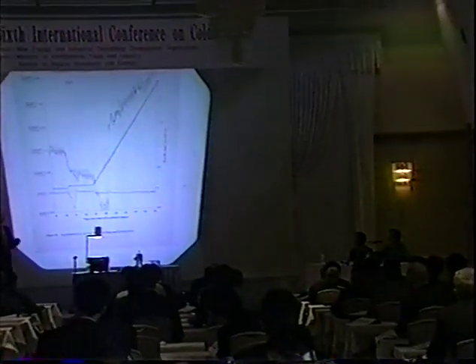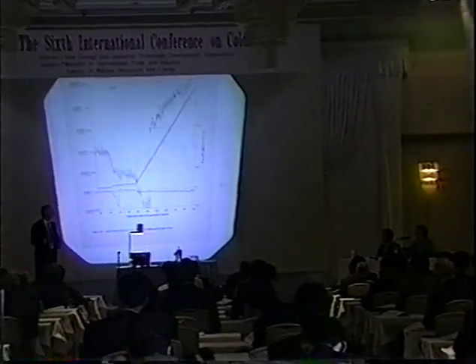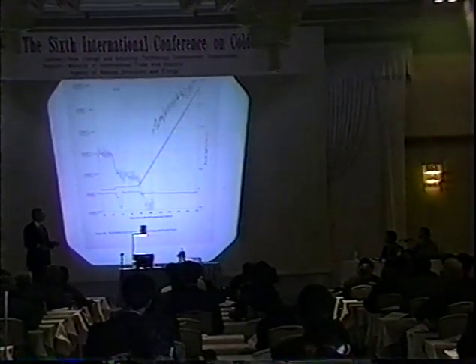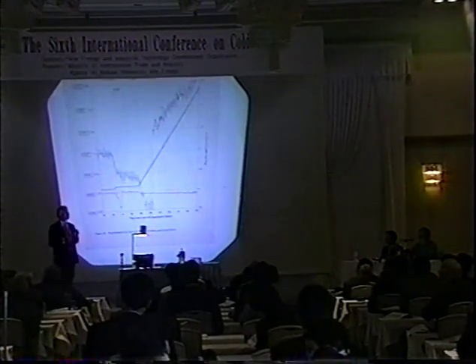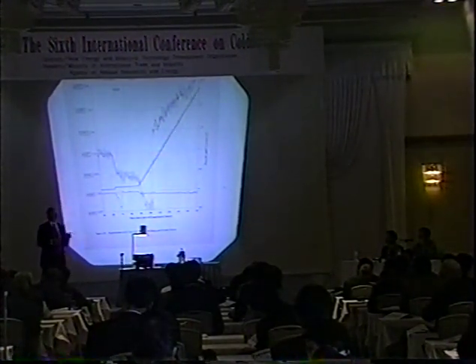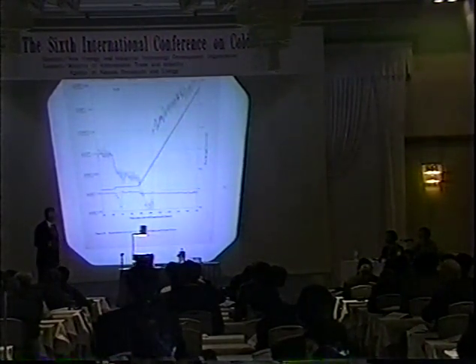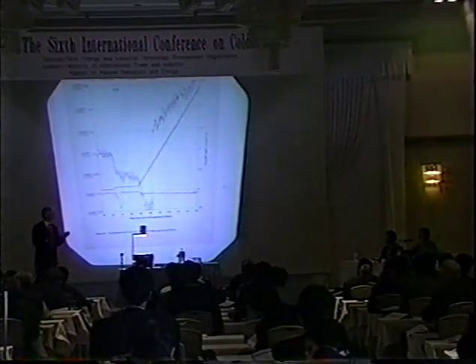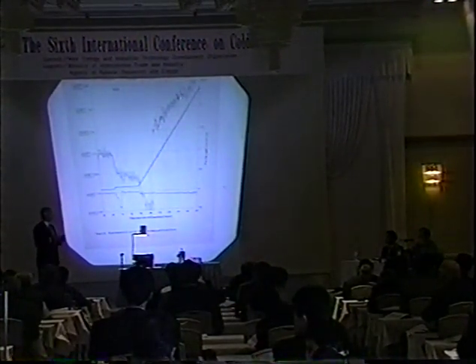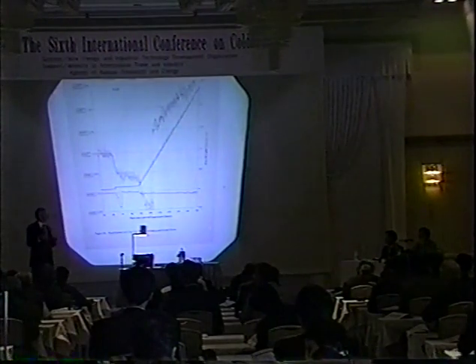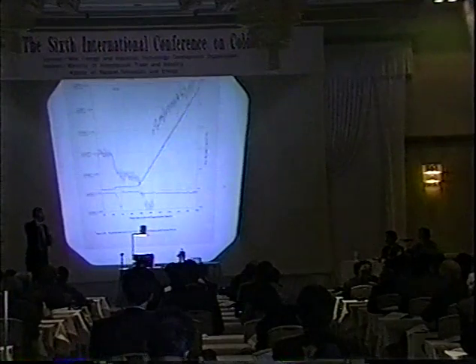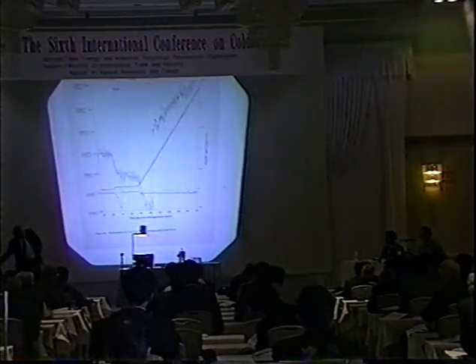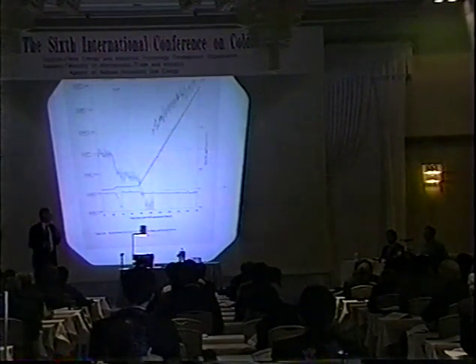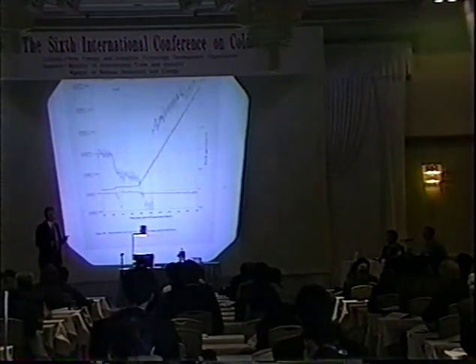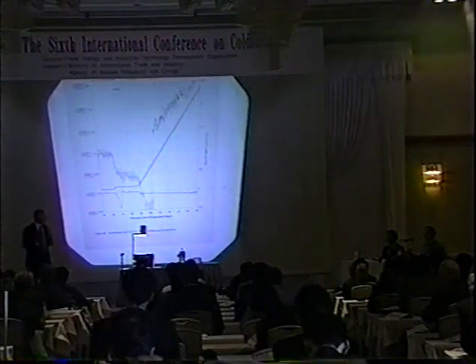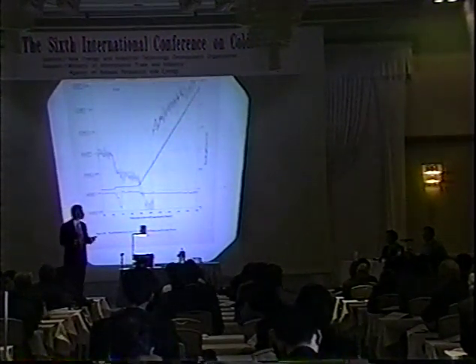We've made attempts to deliberately oscillate the loading level by fluctuating the temperature, oscillating the current. It's very, very difficult to achieve stable oscillations in the loading, which is what you must have if you have a net flux through the interface, by any means, which doesn't result in a net deloading. What tends to happen is you never gain as much on the up as you lose on the down. So the cycle just takes the cathode down in loading. So we are not able to produce the fluxes that natural effects within the system produce.